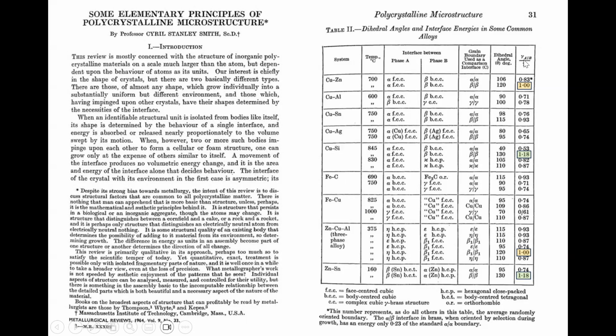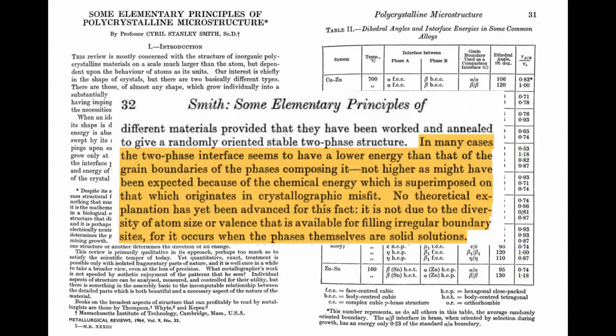And this is the ratio of those 2 grain boundary energies. And I've highlighted in green the 2 which have got the AA grain boundaries being lower energy than AB. And then there's another 2 here, which they're the same. So generally they're not, right? Which is almost completely counterintuitive. And Smith himself did remark that this was counterintuitive.